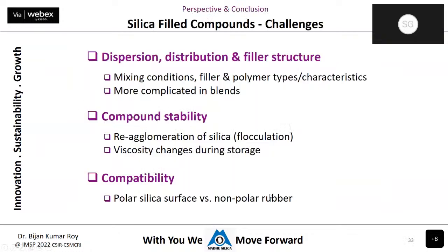Now I come to my last slide, the conclusions. Even though silica is widely used and its usage is gaining more and more, it has many challenges. First of all, dispersion, which is due to the polarity incompatibility, because silica is polar whereas rubber polymers are especially non-polar. So the dispersion or distribution of silica is a challenge. Then compound stability: since silica is surrounded by hydroxyl groups, many hydrogen bonds form, causing re-agglomeration of silica, called flocculation in rubber technology. It is a disadvantage because when you mix a silica compound and keep it for 2 to 3 hours and then process it again, it becomes very hard. That is another challenge, and obviously compatibility.